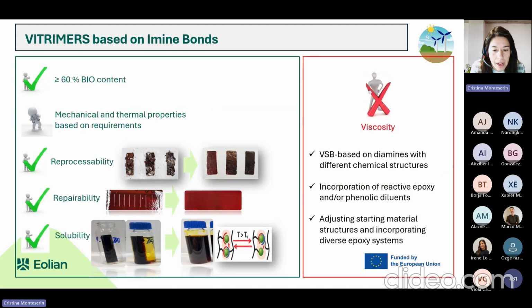Once we have the vitrimer, in this slide we present some of the key results obtained until the moment for the imine-based vitrimers developed within the EOLIAN project. On the left, you can see that some of the developed materials achieve a bio-based content of over 60%, demonstrating our progress toward sustainable formulations. The vitrimers also exhibit mechanical and thermal properties in accordance with common epoxy-amine thermosets with aliphatic structures. We are still working to achieve the requirements for the wind blade application. But we have also confirmed the processability and repairability, as shown in images where the materials were reshaped or healed after damage.